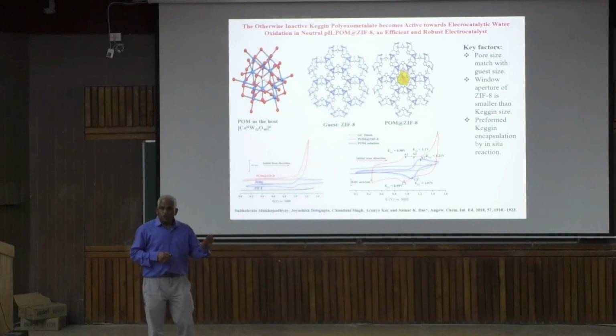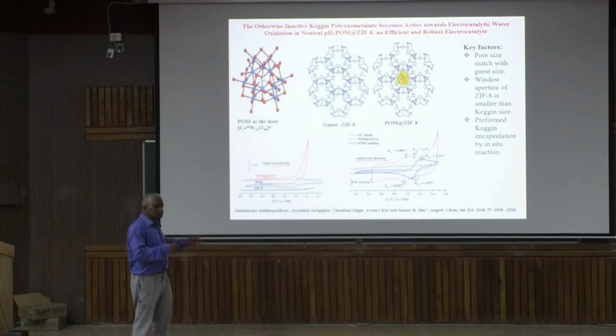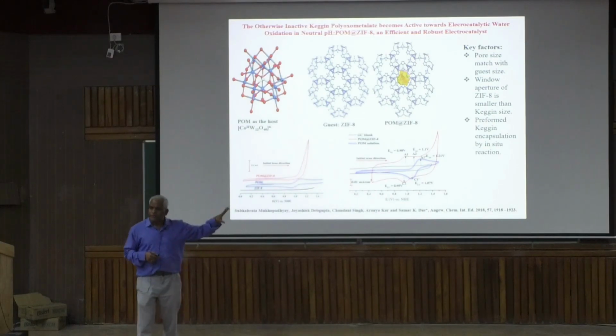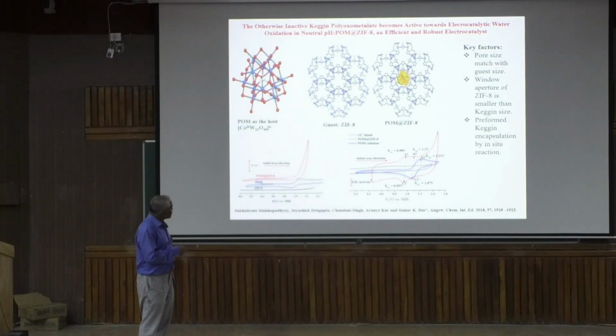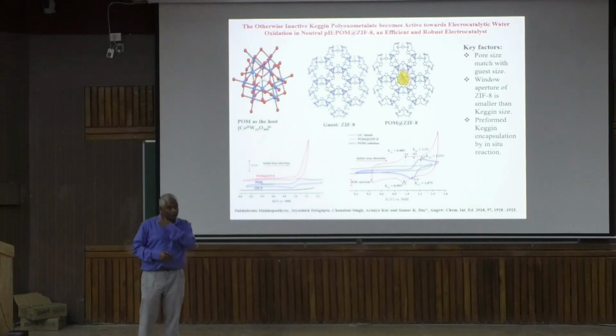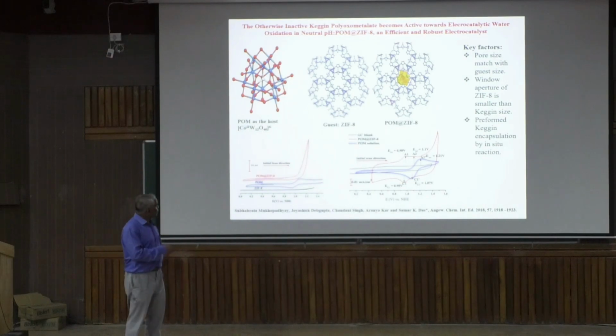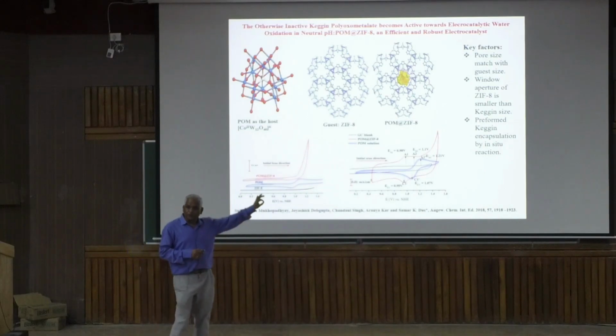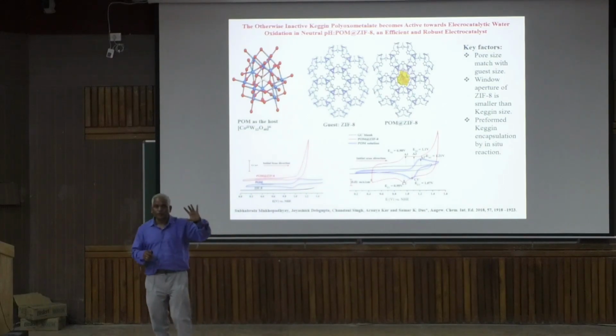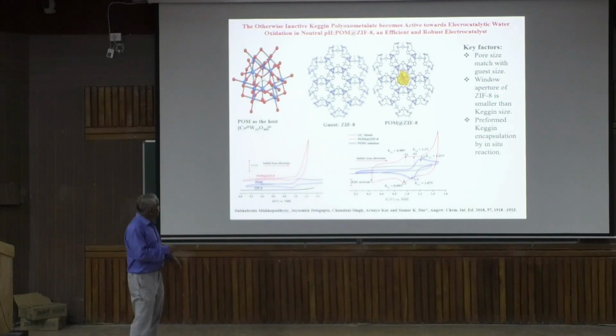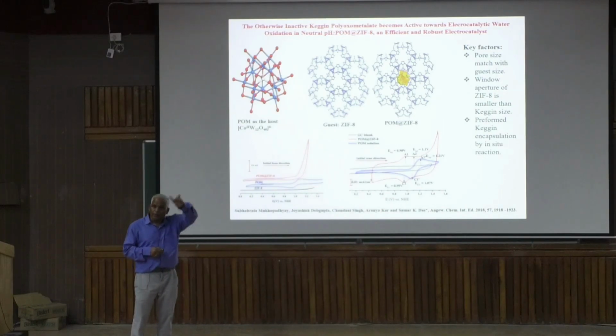Now let me tell you, we don't have control of the encapsulation. Control means we cannot say that we want all cages to be filled. No. Whatever way we did, you always find that one cluster goes in 7 cages. We have kept less amount, more amount, but if we put very little, we cannot get all filled. Generally, we get one cluster per 7 cages. That we characterize. We don't get a single crystal for this one; we always got a microcrystalline compound. With PXRD and all these things, and the characteristic properties, we proved that this compound got encapsulated, one cluster per 7 cages.